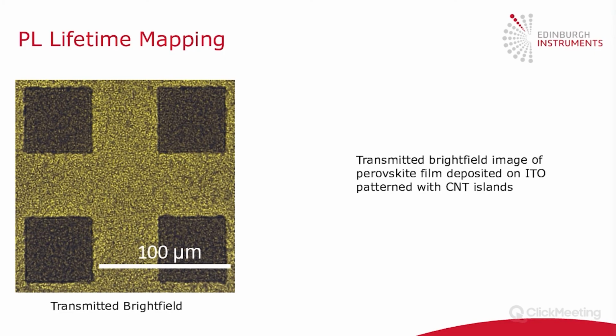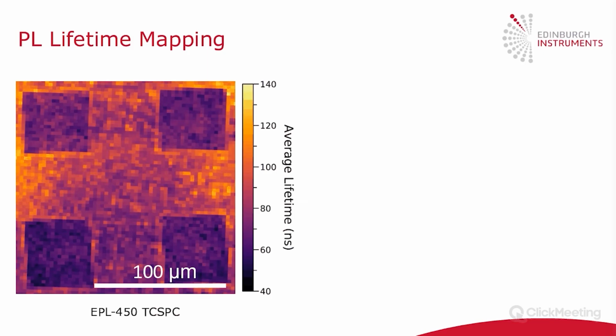So I'll show you here an example of this. This is the same perovskite carbon nanotube sample, but now we've zoomed in just to look at 4 squares. This is a transmitted bright field image. And now if we excite the sample and measure the lifetime, we get this photoluminescence lifetime image of the sample. Regions that are shown dark here have a low average lifetime, and the regions that are brighter have a higher average lifetime.